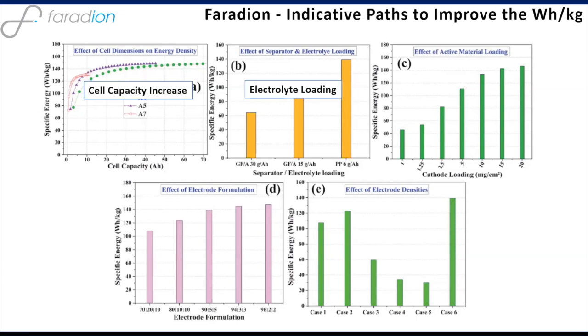Secondly, electrolyte loading. Generally speaking, we measure that in the lithium ion or sodium ion battery industry in how many grams per amp hour of electrolyte you add. If you develop a new cell chemistry, this is maybe one of the last things that you fully develop. But we know that there's a good way for us to go in terms of optimizing the grams per amp hour of electrolyte that we use. If we get that down to where we need to be, that has a benefit not just in boosting the specific energy, but also is a very handy cost saving, because electrolyte now is pretty costly.